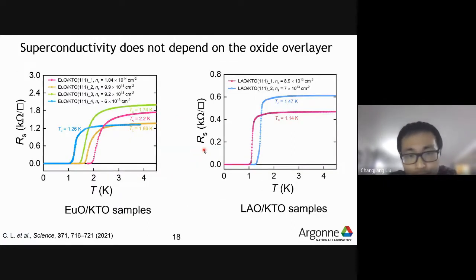So as I mentioned, we not only grow europium oxide on KTO, we also grow lanthanum aluminum oxide, or LAO, on top of KTO. We found that in the LAO KTO system, the superconductivity can also happen. So this means this superconductivity does not depend on the specific oxide layers chosen to form the 2D electron gas. You can use any other oxide top layer. As long as you can get a conducting interface, you can actually achieve superconductivity at a low temperature.